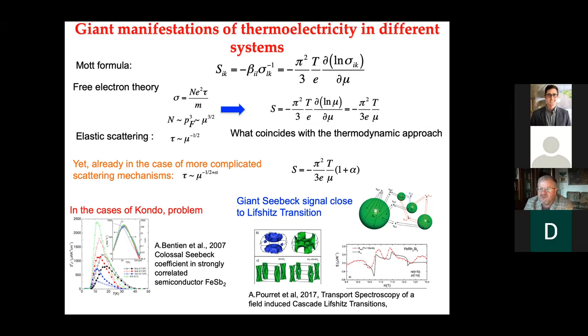This is, for instance, the Kondo effect. This is a topological transition, when the Fermi surface changes its topology, the number of components of connectivity. For instance, very recently, Alexander Pourret and I did a study of transport spectroscopy of field-induced cascade Lifshitz transitions. Today, in heavy fermion systems, you can have even 15, 20 such transitions when the Fermi surface changes topology. It is possible to study them by means of the Seebeck coefficient behavior and characterize these transitions.